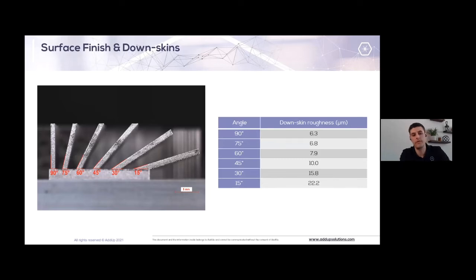And just further demonstrating that here, showing the very significant overhang and shallow angle of 15 degrees, we can actually achieve surface finishes still down at 22 microns. And for that vertical surface, we can get as smooth as 6.3 Ra microns.